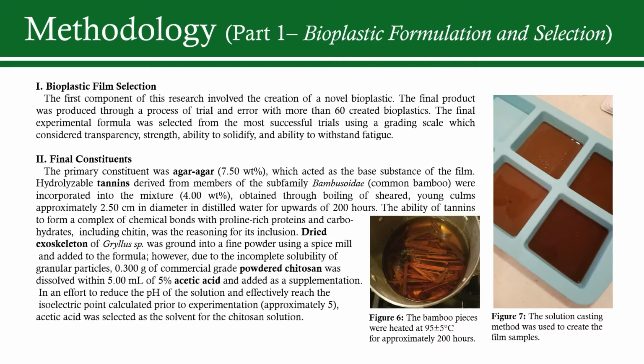So to create the bioplastic, fresh bamboo culms were cut into small pieces and boiled at around 95 degrees Celsius in distilled water for approximately 200 hours until the solution darkened, indicating the release of tannins. To ensure the solution was the correct concentration, colorimetry was used to take a turbidity reading.